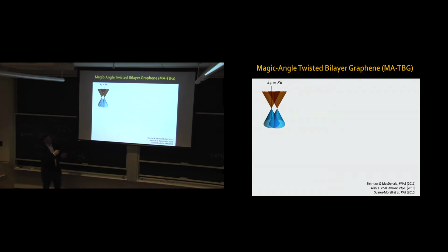This would be the situation if electrons in one layer didn't see the other layer. But when you put two graphene sheets on top of each other, they're just 3 angstroms apart, so the electrons are very much aware the other layer exists and can tunnel between the two layers. This means that at the intersection of the Dirac cones, at those degeneracy points, there is level repulsion, similar to bonding and anti-bonding states in a molecule, so that a gap opens due to interlayer interaction.